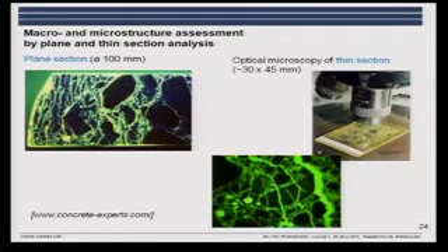I find it very useful to start at the meso or macro level, because you can end up looking at a very small place which is not representative and where you don't capture these macroscopic effects. So depending on what type of information you actually need, you should also look at the entire sample. And with this fluorescent technique, when you use the UV lights, you can see the cracks coming up so easily. It's the same technique with the impregnated samples we use for the thin sections, but here they are, as you can see, very thin, and we can look through them. And if you are to compare with standards, it's important that they have a given thickness. And this is this 20 microns, which is typically used.